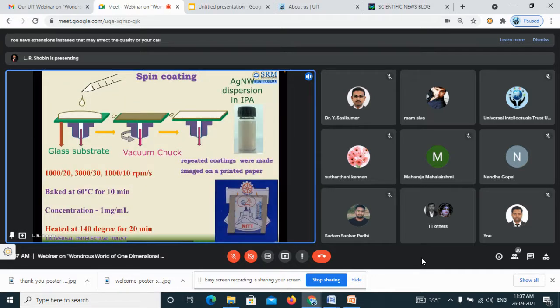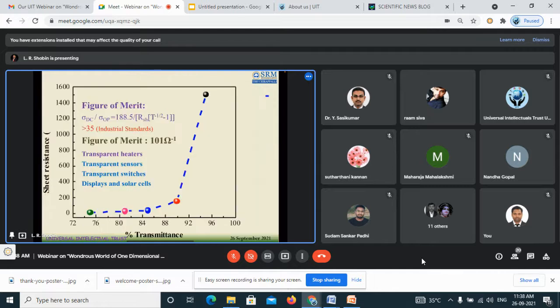So what I will do is take a glass substrate, fit it in a vacuum chuck, and pour a couple of drops of this silver nanowire dispersion in IPA, and I will get a transparent conducting film which will have a resistance of less than 100 ohm. If you see that plot over here, you can see the resistance of the film. Say for example, over here the transparency of the film is around 85%, and it will have a resistance of less than 100 ohm.